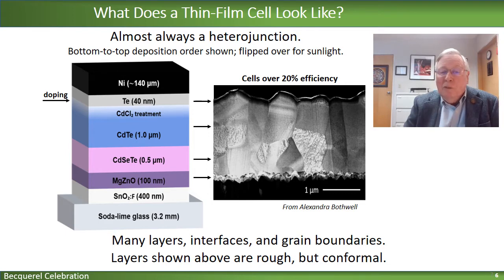They're not smooth like you see in the schematic, but if you look carefully, you can see that they're all pretty conformal or continuous, which is good, so that electrically they act not that much differently from the schematic. You also notice that the individual grains there are about the same thickness as the individual layers, which is also good. But what is maybe not so good is that there are interfaces in between the grains, what we call the grain boundary issue, and that's where some of the passivation research has come into play. So what we have here are layers which are rough, but they're still conformal.